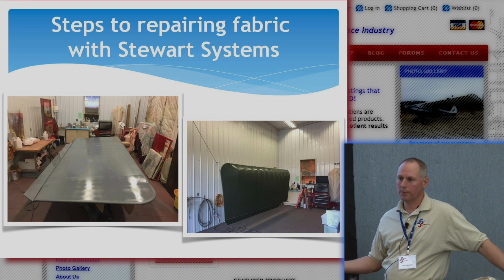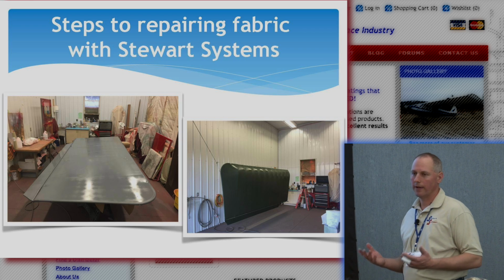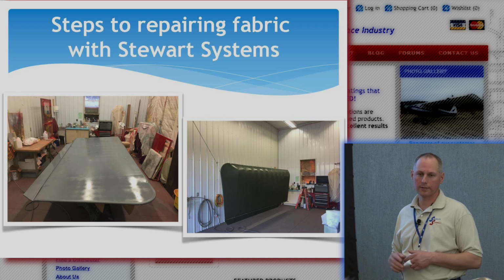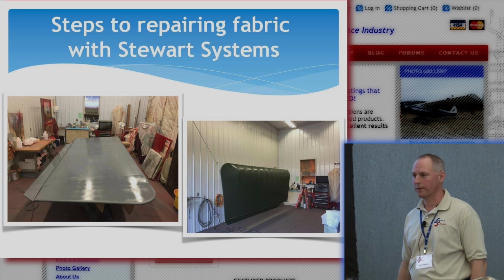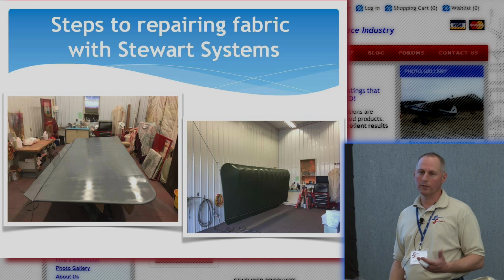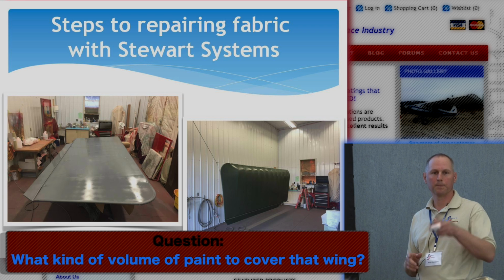When you do the paint, it's pretty forgiving on the environmental conditions. We're looking for a 65 to 85 temperature range. Humidity 20 to 80% is good. In our case, we have a heated floor, so if the humidity is low in the wintertime, we just hose the floor down and it comes right up. So that makes it really nice. If you have really low humidity, you're going to get some orange peel and some dry spots. It's a little tricky.